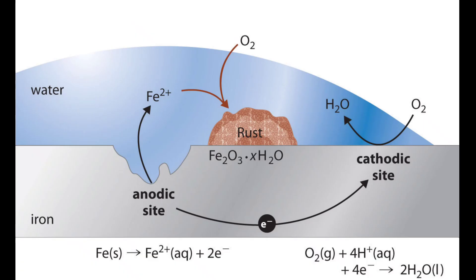The heterogeneity of mild steel in the hull of the ship, along with factors such as non-uniformity of hull plate thickness, paint thickness and quality, variation in the ship structure, welding seams, dissimilar metals, and oxygen content in the seawater combine to cause areas in the hull to work as cathodes and anodes, thereby forming a galvanic cell.